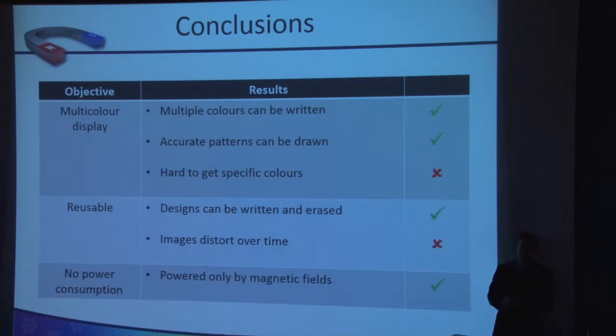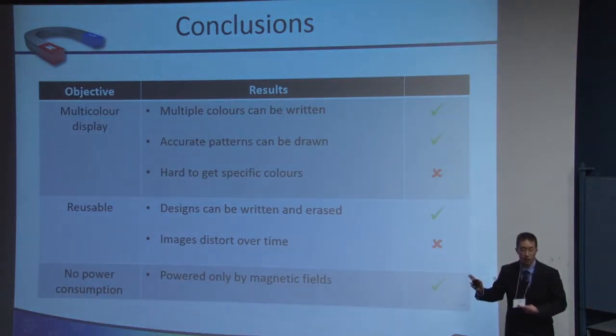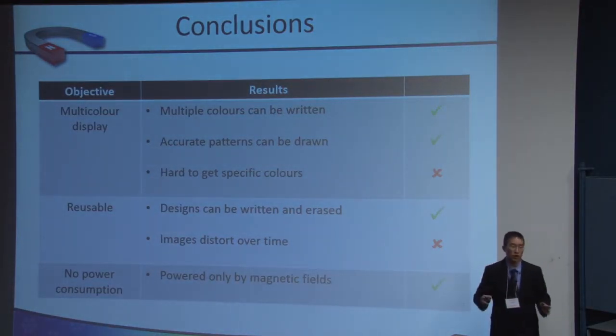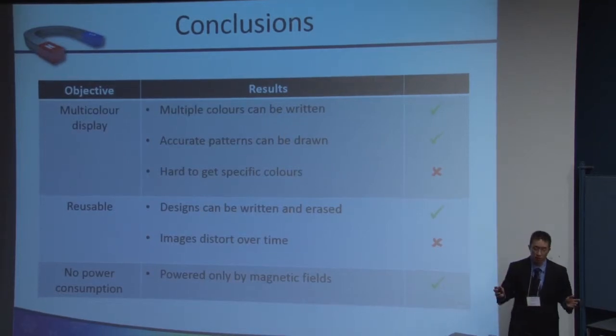However, an issue we have is that the images tend to distort over time due to sedimentation. This is a combination of both gravity and the fact that there is the magnetic hysteresis layer underneath, which exerts a constant magnetic force on the particles to drag them down. However, we were able to achieve our objective of having no power consumption. All that's required to write and erase are just simple magnets.